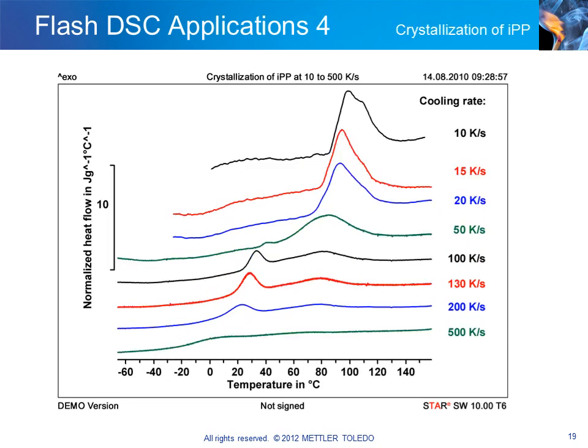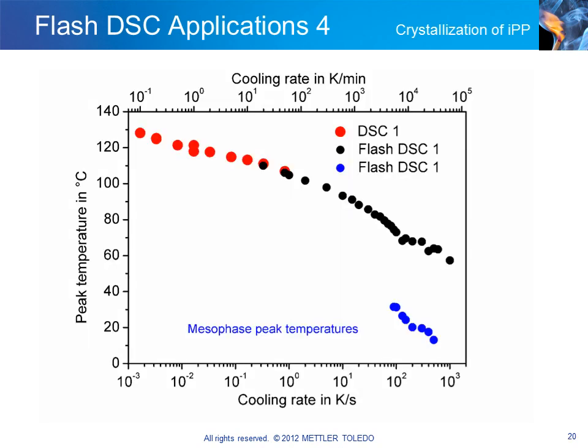The slide displays cooling curves obtained from measurements performed on isotactic polypropylene at cooling rates between 10 and 500 degrees per second. The curves show how the crystallization peak shifts with the cooling rate. This diagram summarizes all the measured peak temperatures as a function of cooling rate. The measurements were performed at cooling rates between 0.1 and 1000 degrees per second. Several measurements were also performed at cooling rates between 0.02 and 0.8 degrees per second using the conventional DSC-1. The results are shown as red points. The black points are the measurements obtained using the Flash DSC-1.